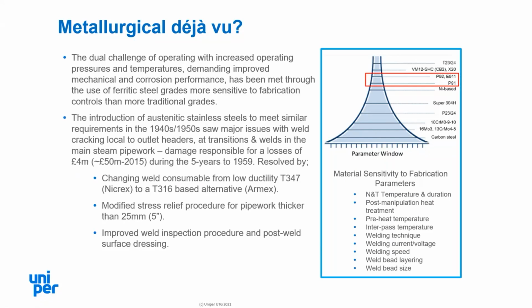We've certainly been here before, though. The introduction of stainless steels in the UK followed its earlier introduction during the 1940s and 1950s on US plant. The plant in the US was operating at 540 centigrade. In the UK, it was 560, 570 degrees centigrade. And as a result, we saw very early issues with weld cracking local to the outlet headers, at transition pieces, and also at welds in the main steam pipe work.